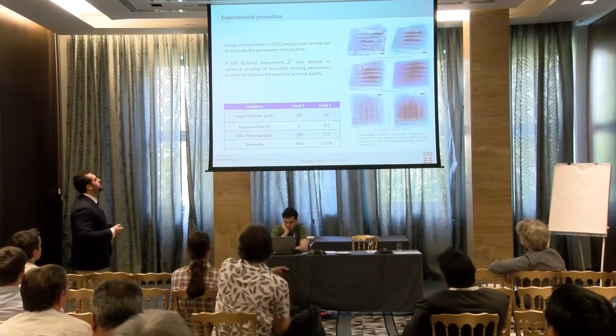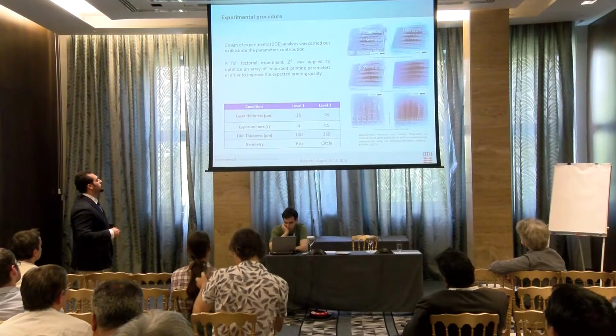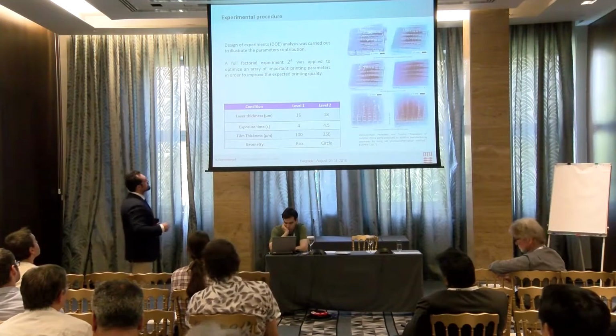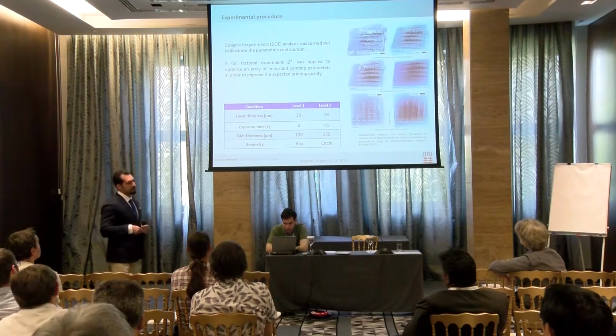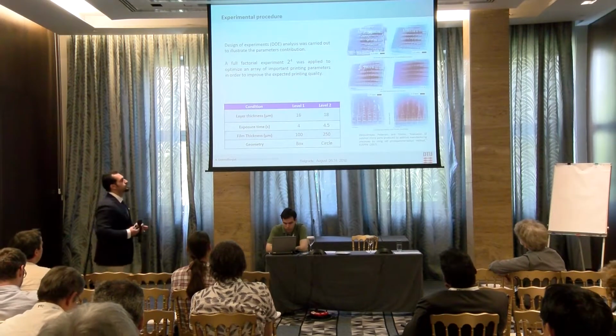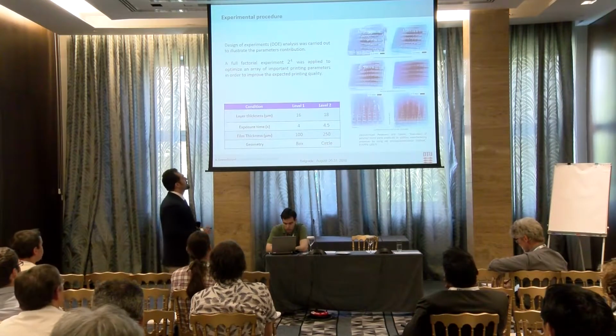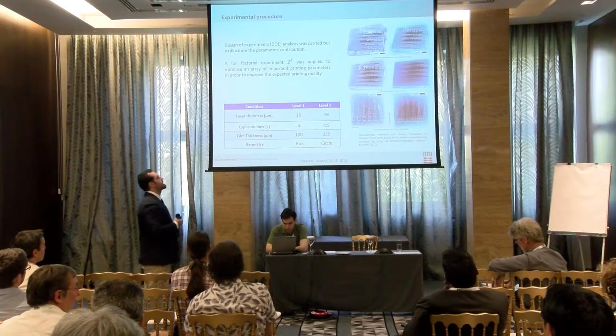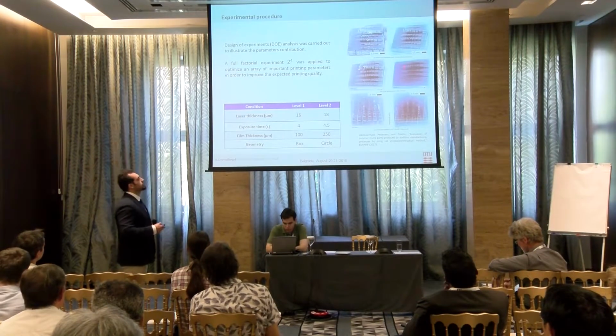Here is the result from the DLP. We use different conditions and parameters such as layer thickness, exposure time, film thickness, and the geometry. And then in a full factorial experiment, we try to analyze the contribution of each parameter. As you can see, the results were improved from this geometry, which all stuck together, and we got a much better result by improving the parameters.